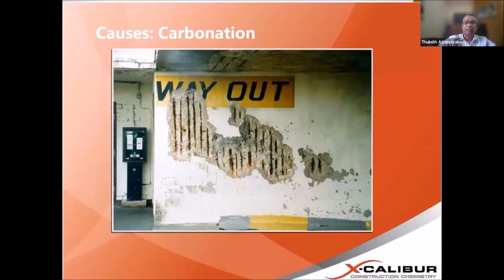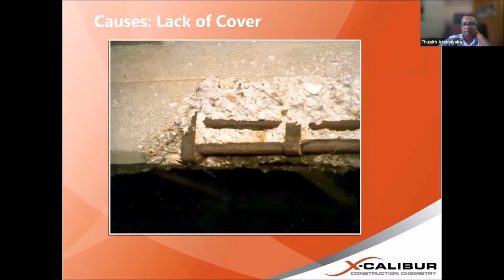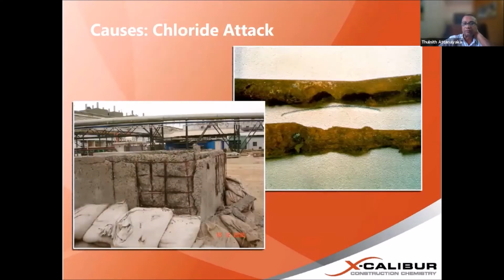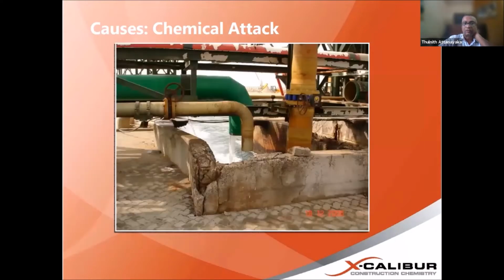So this is the carbonation. You can identify this with the picture. The entire reinforcement bar is covered with corrosion. So the front has already touched the reinforcement bar. Lack of cover. Again, lack of cover. So you can see this when it comes to corrosion attacked by chloride. You can see the corrosion pits, not like carbonation. Here and there, the small pits are visible. So this is the chemical attack.